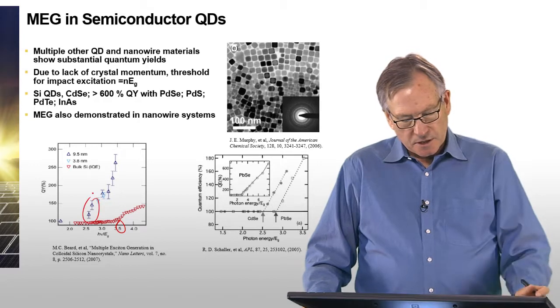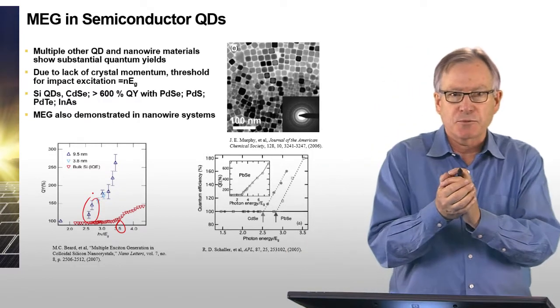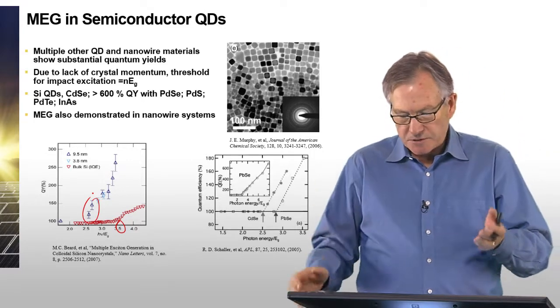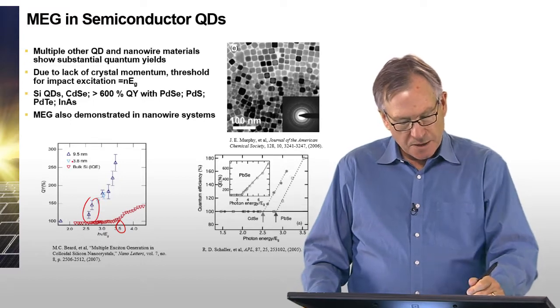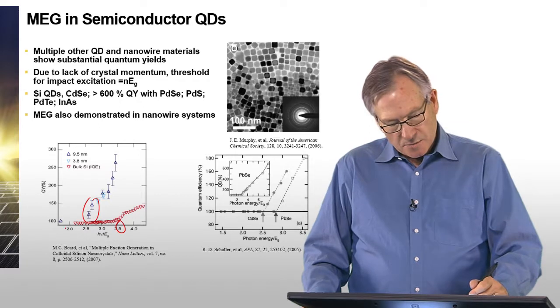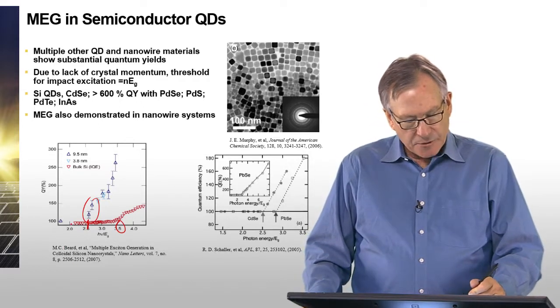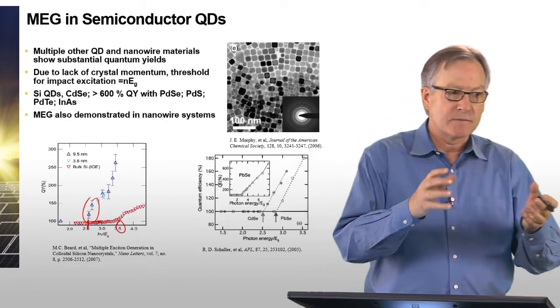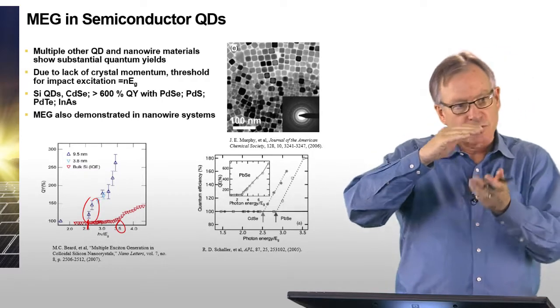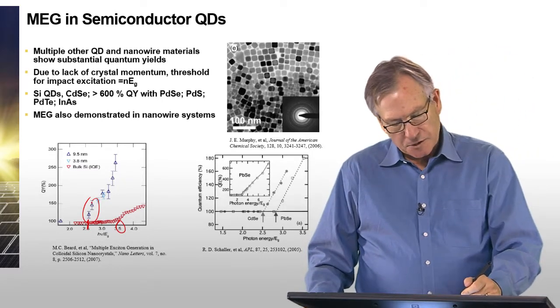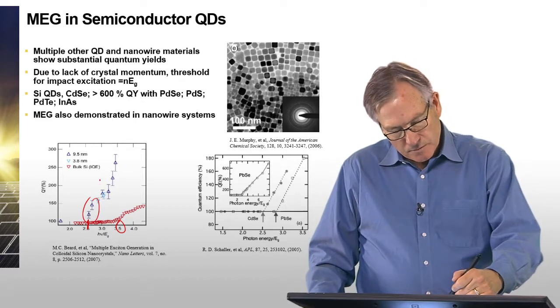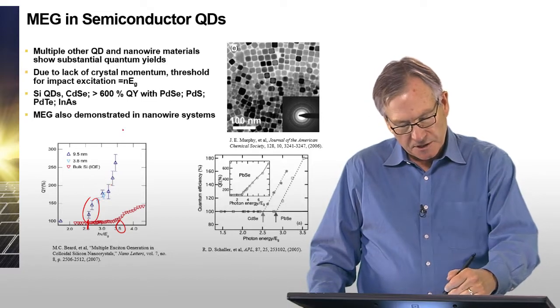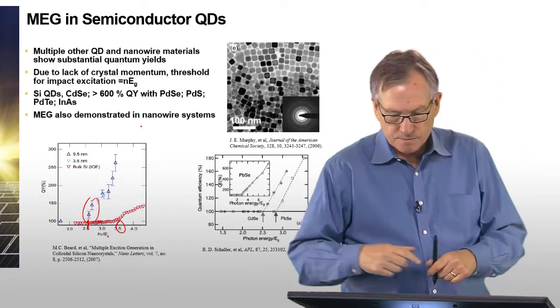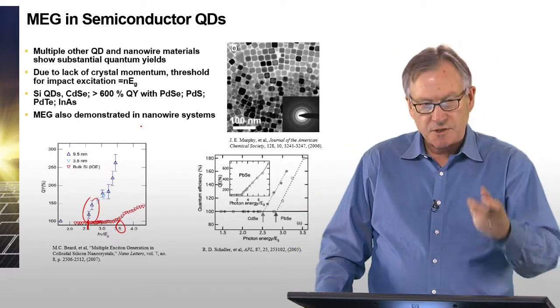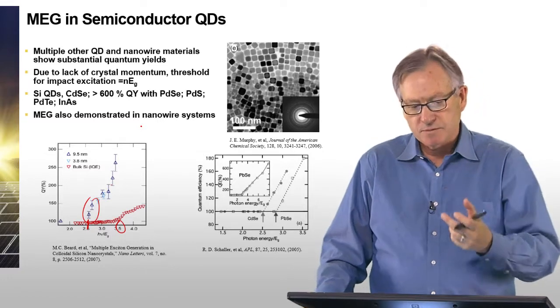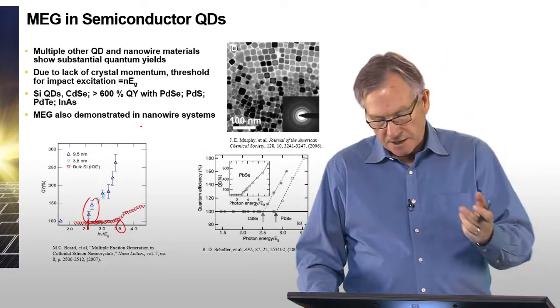On the other hand, if you look at silicon quantum dots, fabricated either by colloidal assembly, as I mentioned, or by growing them in a matrix of silicon dioxide, these silicon nanoparticles with different diameters, 3.8 nanometers, 9.5 nanometers, basically show a threshold which is higher than twice the band gap of bulk silicon, and that's because of confinement. Because you make a nanoparticle, the energy band gap is increased, so twice the energy band gap is slightly higher here. But then there's a sharp threshold, and the quantum efficiency jumps up, not perfectly step-like, but to about 200% here, and then it keeps on going. You can see that silicon nanoparticles show effective multi-exciton generation. So there's a lot of interest in whether we can make silicon solar cells in which we introduce silicon nanoparticles and get multi-exciton generation.